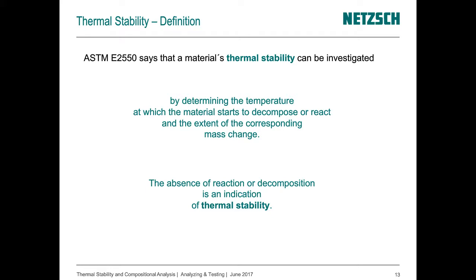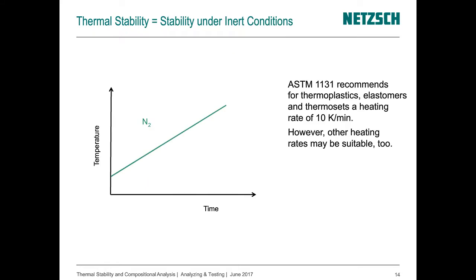And how thermal stability is carried out in practice, we can see here in this scheme. It's very often just a heating segment under inert conditions. And for polymers, inert conditions mostly mean nitrogen atmosphere. The heating rate in the ASTM E1131 standard, for example, is recommended to be 10 Kelvin per minute, but of course it can also be another heating rate. The typical range of heating rate is between 5 and 20 Kelvin per minute, but most of the instruments on the market can also realize smaller or larger heating rates. It always depends on the sample properties and sometimes also on the number of samples to be measured.